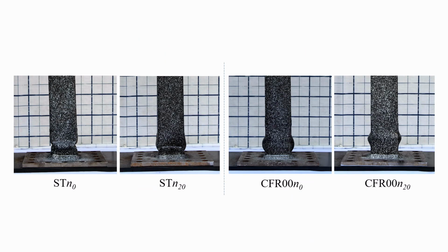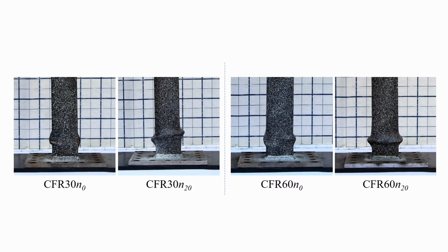So the hollow steel tubes failed by inward and outward buckling, and then they developed fractures at a given displacement rate. Whereas the concrete-filled steel tubes, they all failed by outward buckling and crushing of the concrete. And then at about drift ratios of 10%, they started to develop fractures at the buckling area. So these are the ones for the R30 infilled tubes and R60 infilled tubes.